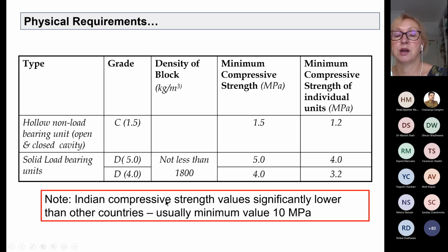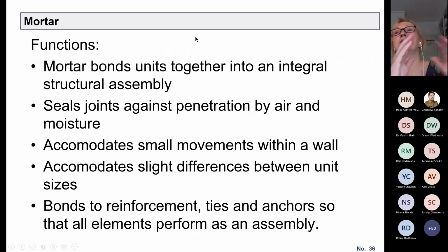Indian compressive strength values are significantly lower than other countries. Usually the minimum value is 10 megapascals in other countries. But in India, the lower values are acceptable right now, because I guess the blocks were used for low-rise buildings or for non-load-bearing structures. In that case, it is not that important what the strength is, but for load-bearing masonry, as we will discuss, it is really important what the strength is, and it has to be higher. So these were the masonry units that we covered: the bricks, blocks, clay bricks, fly ash bricks, and blocks.